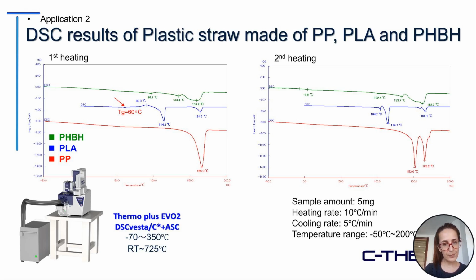The thermogram of the PP was much simpler. In the first heating scan, we just see the melting temperature at 160, and in the second heating scan, we saw two endothermic peaks, which again are related to the melting temperature of the PP.